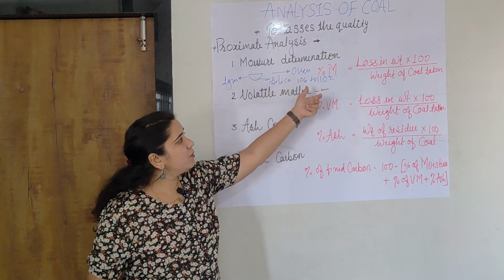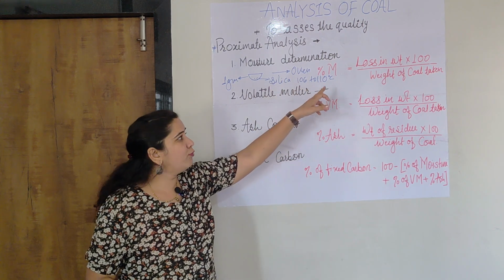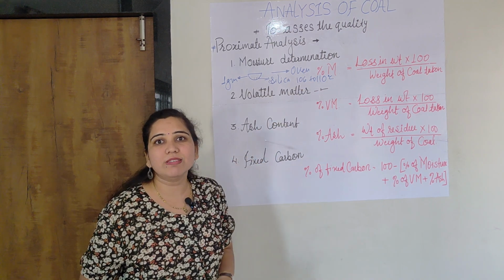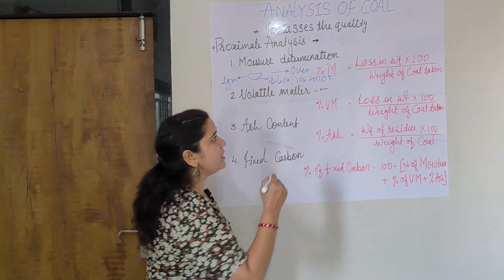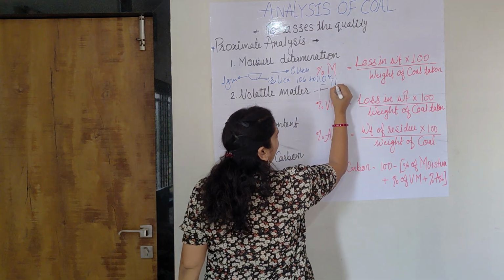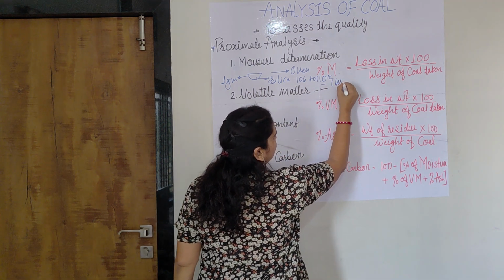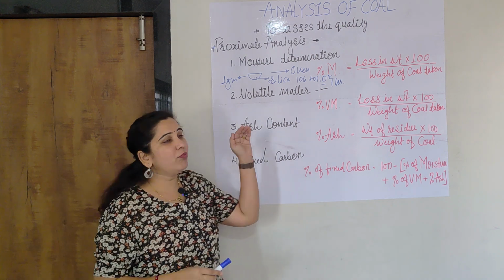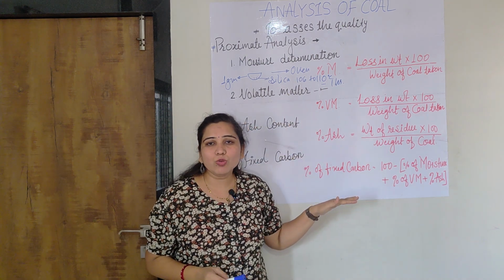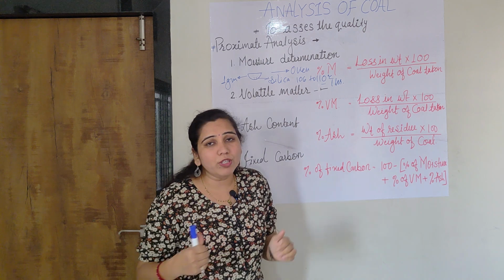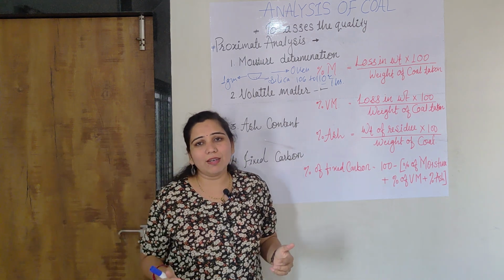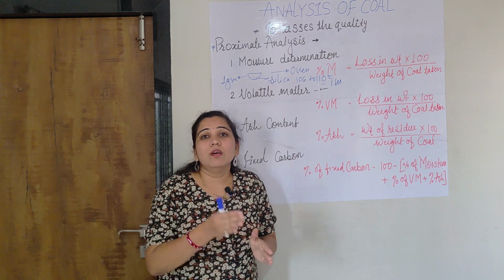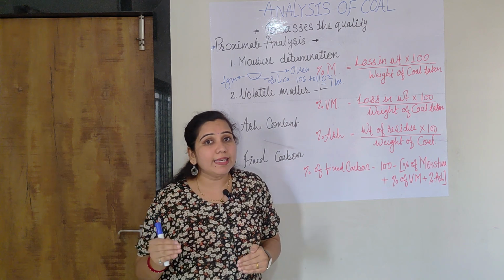So the silica crucible is put into the oven for a temperature range of 105 to 110 degrees Celsius, for about 1 hour. For 1 hour, the silica crucible is to be put into an oven. Then after 1 hour, remove that silica crucible. When it is removed, it must be at a very high temperature, so first cool it to room temperature, then put it into the desiccator.